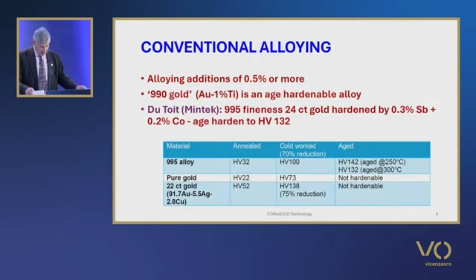If we look at conventional alloying, here we're talking of adding alloying metals in amounts of at least 0.5% or more. The addition of 1% titanium to pure gold to produce 990 gold has been referred to previously. Other significant improvements to 24 and 22 karat golds have been described using conventional alloying approaches. Dutoit and co-workers at Mintek in South Africa showed that a 995 fineness 24 karat gold containing 0.3% antimony and 0.2% cobalt can be age hardened to a hardness of 132-142 Vickers, depending on aging temperature, as shown in the table.